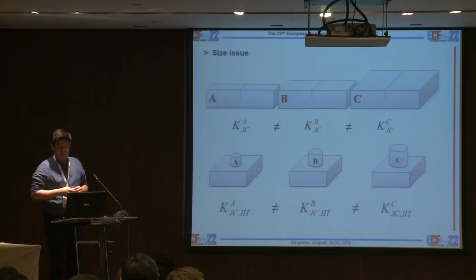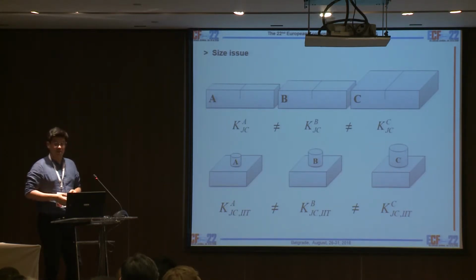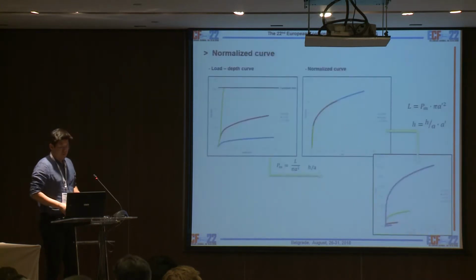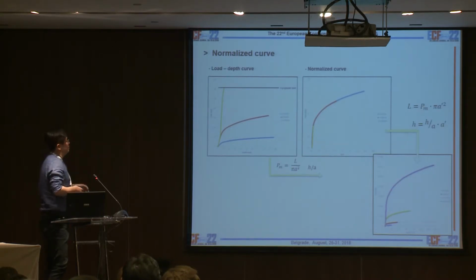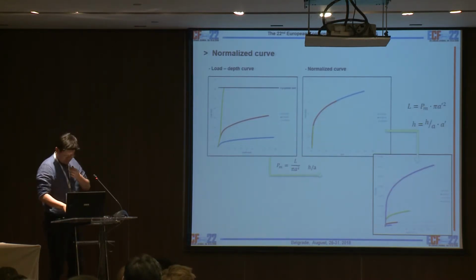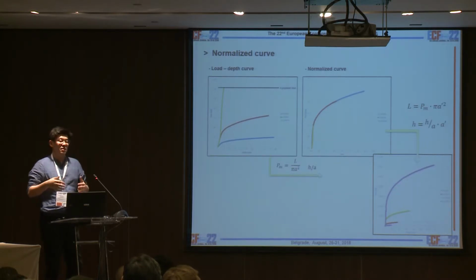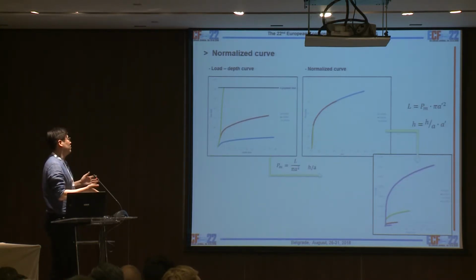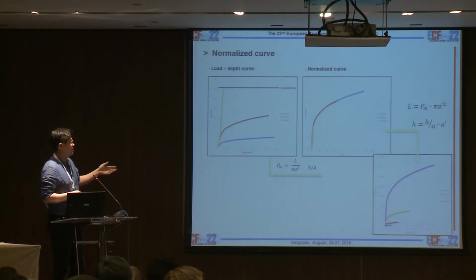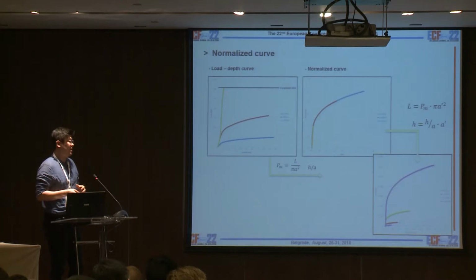We know the fracture toughness value should be validated with the thickness condition. And the indentation curve also varies according to the indenter size. To overcome this barrier, we use normalization. As you see in the left picture, the larger the indenter size, the higher the indentation curve goes. But if we normalize it with the indenter size, we can get a mean pressure versus penetration depth h over indenter size a curve.